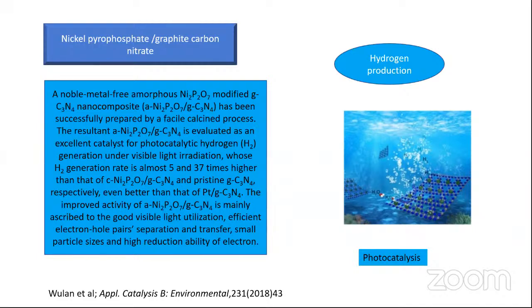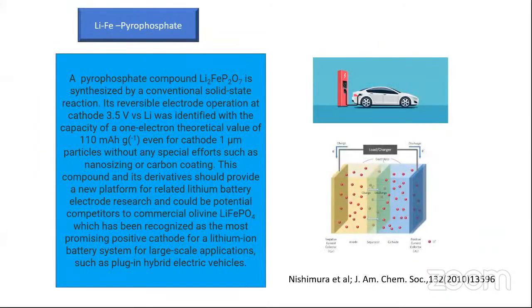Again, it is the lithium iron pyrophosphate. This is also related to energy. A pyrophosphate compound, lithium iron pyrophosphate, is synthesized by conventional solid state reaction. Its reversible electrode operation at cathode 3.5 volt versus lithium was identified with the capacity of 1 electron theoretical value of 110 milliampere hour per gram, even for the cathode of 1 micrometer particle without any special efforts such as nanosizing or carbon coating.